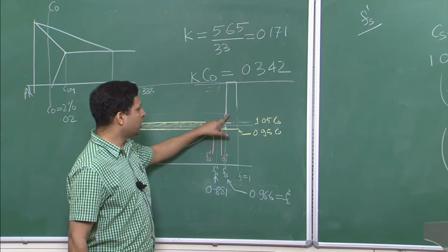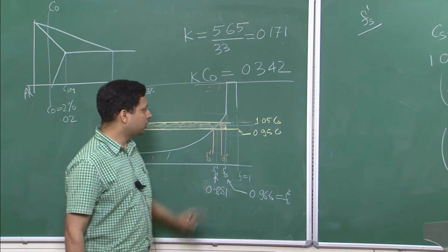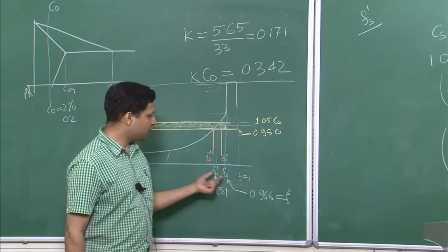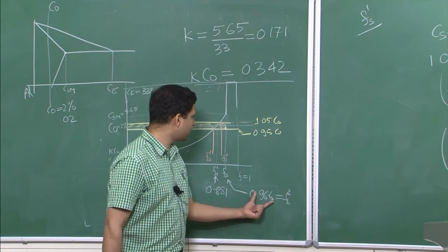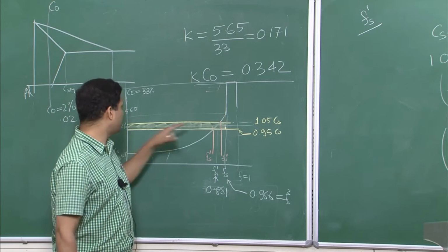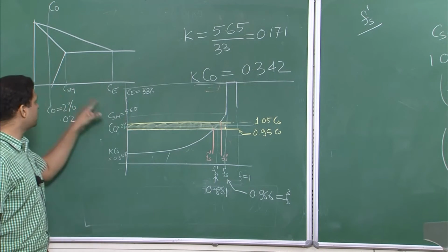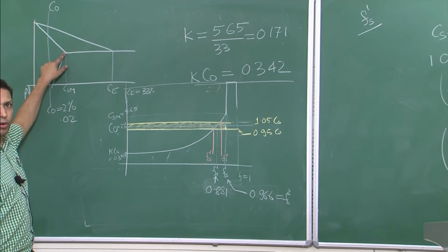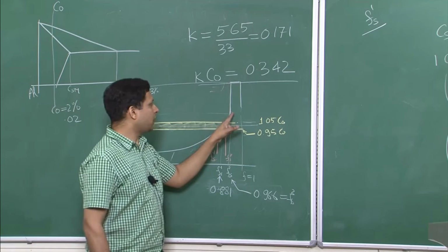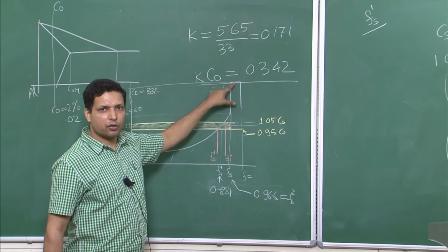So, at that point you are getting something like a eutectic. This is another important aspect: 0.966 is the value at which you reached the CSM, the solute concentration at the leftmost point of the eutectic, and that is also the point where the liquid reached the eutectic.